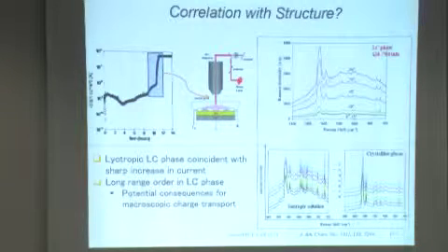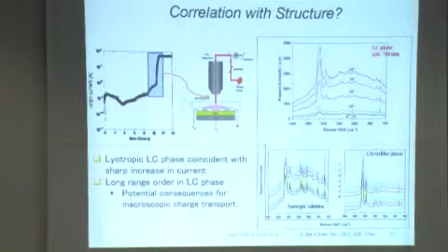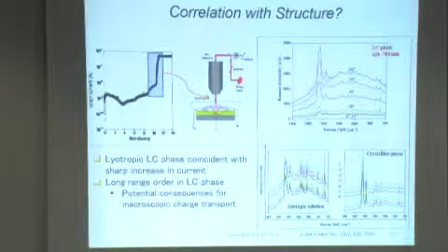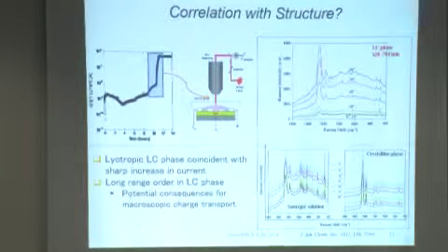All right, so what we were interested in determining is whether that liquid crystalline phase is coincident with the increase in current that we're seeing, and if that's the case, can we now induce long-range order in these films using a liquid crystalline phase, and what are the consequences of being able to do that for macroscopic charge transport?